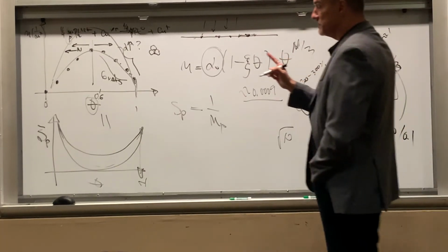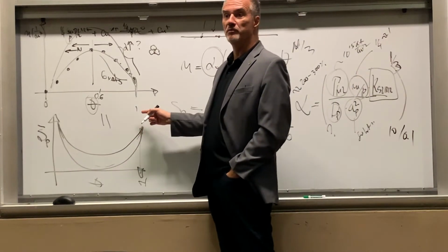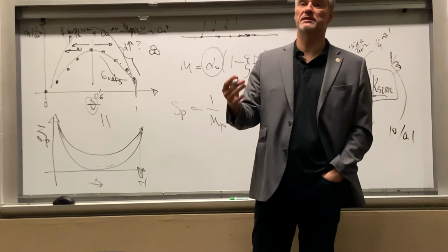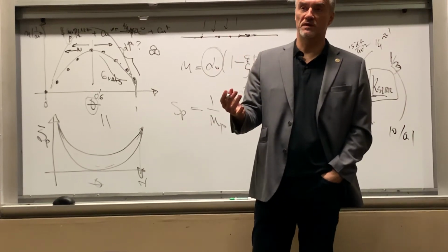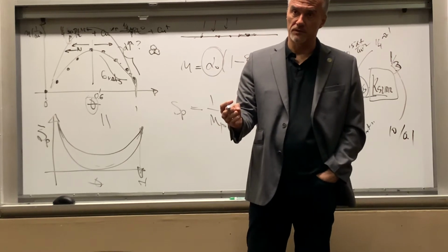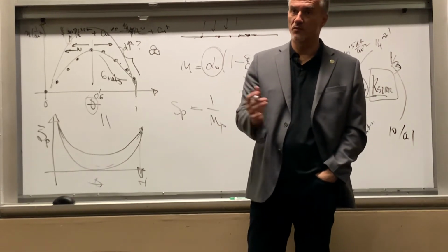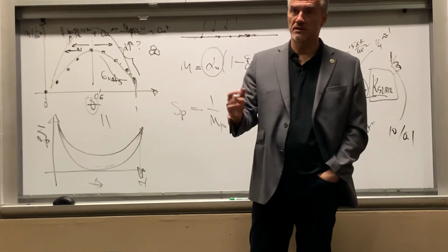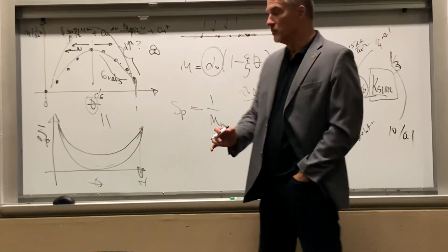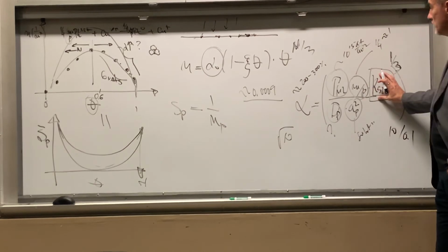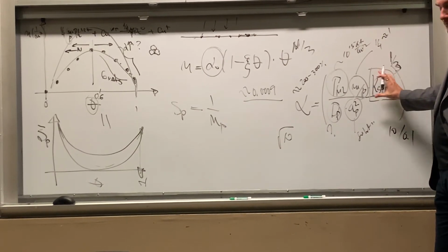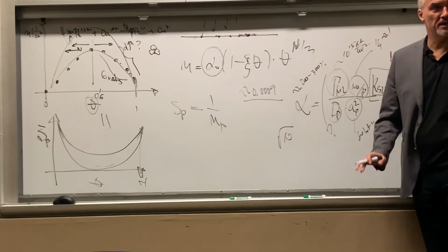Whether you want a catalyst with small clusters or big clusters. Sometimes you want to hinder the activity of the catalyst because it gets poisoned very easily by the product. Then you make smaller clusters. If you want just activity, and you have no problem with intermediate products gluing to the catalyst surface, then you go for big clusters. You want big clusters, you make this small. You want small clusters, you make this big. Okay? Everybody on board with this?